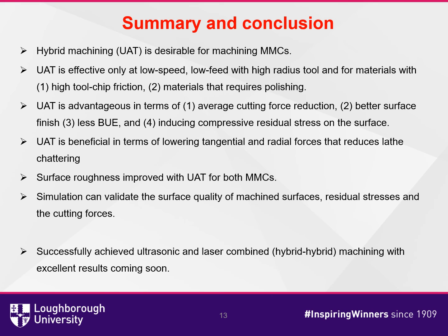UAT is beneficial in terms of lowering tangential and radial forces that reduces lathe chattering. Surface roughness improved with UAT for both MMCs. Simulations can validate the surface quality of the machined surfaces, residual stresses, and the cutting forces. We would also like to mention that we managed to combine ultrasonic with laser, meaning hybrid machining, which showed even better results, and we will report soon.